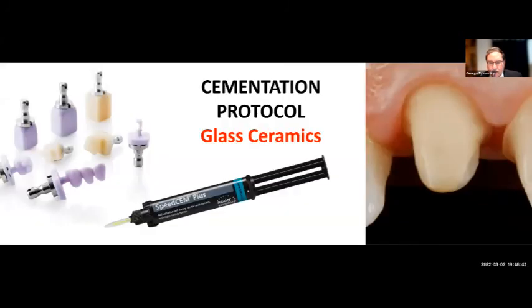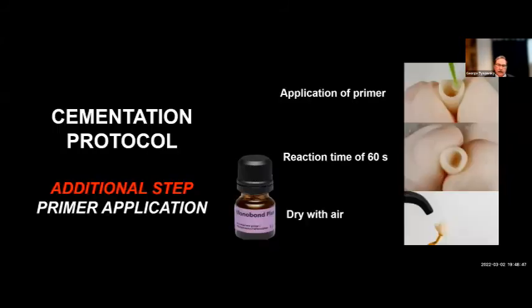Okay. And the final, as far as looking at glass ceramics and the modification of these, the important thing is that we would use the primer for this because we need the chemical reaction with the ceramic accordingly. So using Monobond Plus in this case is a very important criteria to make sure that we get the priming action for the interface of the restoration. So if we look at the techniques, hydrofluoric etching, air drying, then we're applying the Monobond Plus, the primer, to make sure that we facilitate the priming and the sealing of the restoration.